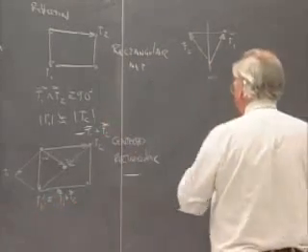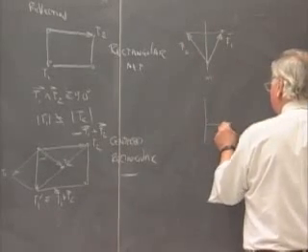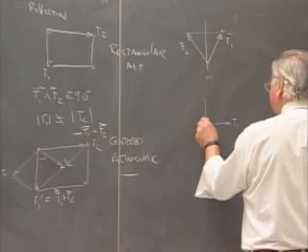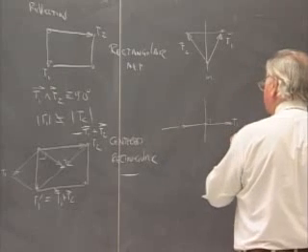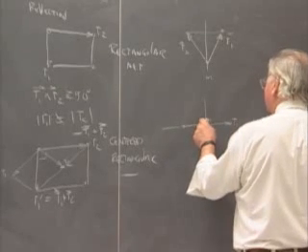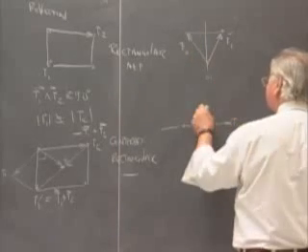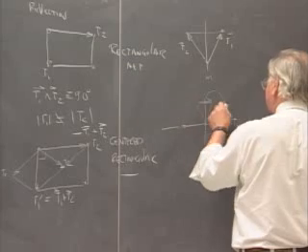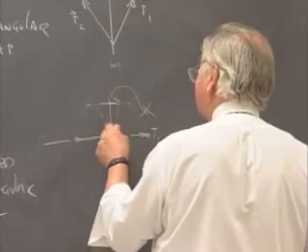Okay, and then the primitive rectangular net, just to remind you again, we said, is there any case in which this is not true? And that case was if you take T1 exactly perpendicular to the mirror plane, and then you define only a lattice row. So that gives you a second choice for T2. You can't pick it anywhere you like, otherwise it gets reflected across just as in the first case, and you have two translations that are not compatible. The only way that they are compatible is if you make the translation T1 straddle the mirror plane, and that's what we've already got up here. So that's how we got the rectangular net.